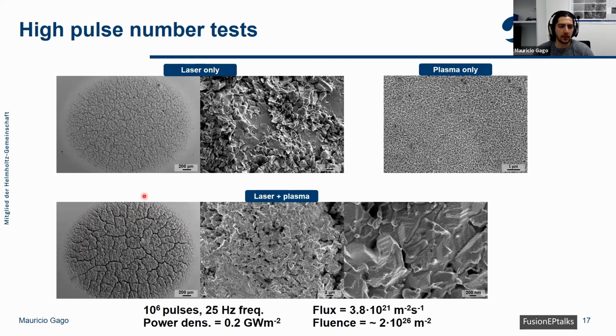So for these tests, we see that after 1,000,000 pulses, with only laser, we have already a crack network. We see surface modification as well, but the cracks are still very thin. And then once we apply also plasma to this, we see the effects of hydrogen embrittlement in that the cracks become broader. And then we see already some small pores on the surface. But again, this time no tungsten fuzz was observed, for example. And no really large cracks were observed as in previous tests with higher power loads.